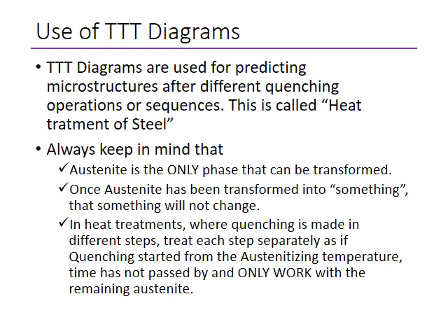So if you further quench that to the martensitic temperature, the 50% of pearlite that you have already created won't change anymore. So that will prevail after the quenching. But the 50% austenite that is still in your material will be the only one that will be able to transform into martensite or whatever the new temperature of quenching requires.